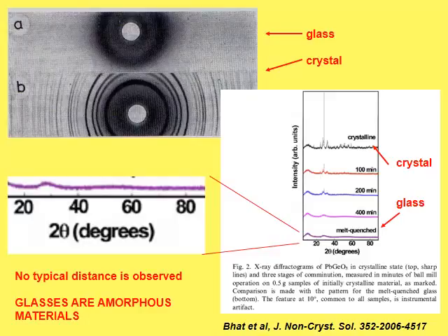Quenching a melt is in fact the oldest method man developed to prepare glasses, as we will see in a moment. Coming back to the paper, the interesting point here is that by using a mill, you can amorphize a crystal. The problem here is that I don't know if this word amorphize exists. Some of you can help me by telling me if this word exists or not, okay? What I want to say is that the sample was transformed from something crystalline to something amorphous under the action of the mill. This process is possible. It's not the rule, it's an exception, I must say.